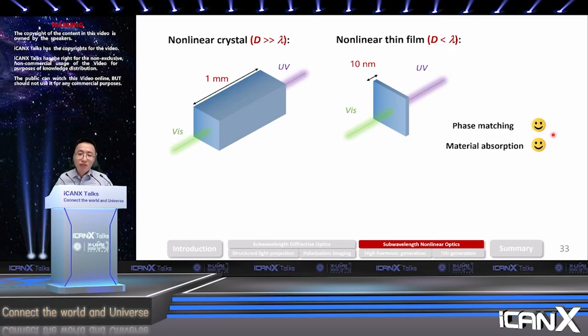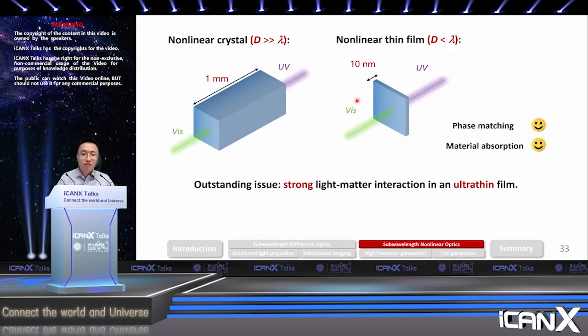But then upon a more careful look, you'll find that there is a big problem here. If for a nonlinear crystal the light-matter interaction length is 1 millimeter, it's 5 orders of magnitude longer than a thin film of only 10 nanometers. So the big outstanding issue here is how can we possibly get strong light-matter interaction inside this ultra-thin, sub-wavelength thin film in order to get efficient harmonic generation?